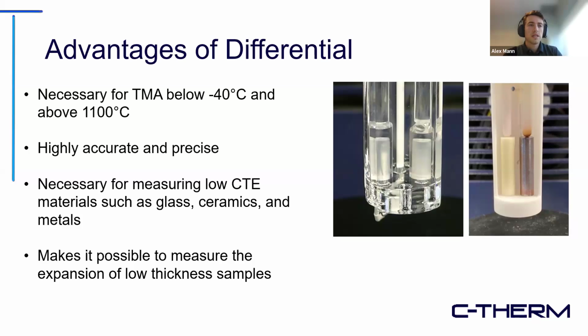Additionally, I did mention earlier that 10 millimeters is the lowest we can go, but that's not entirely true with differential. Because it's so precise and accurate, we can measure samples that are way less than 10 millimeters thick — we can actually measure the expansion of samples close to less than 1 millimeter. We really need differential here for the precision, because the smaller the initial height or length means a smaller overall total expansion, so we're measuring a really small amount of expansion.